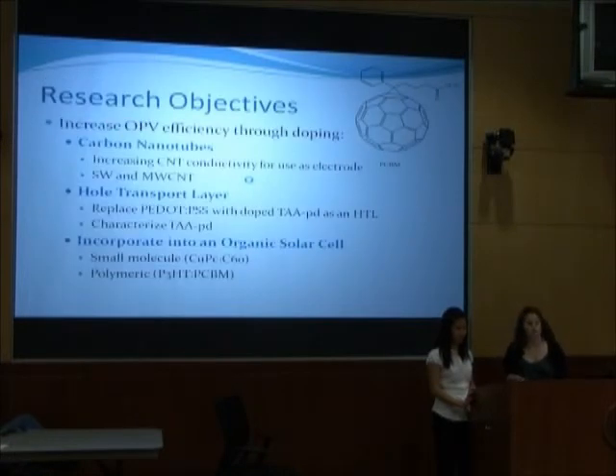In our research, our main objective was to increase organic solar cell efficiency by doping. We doped both carbon nanotubes and hole transport layers. We doped both multi and single-walled carbon nanotubes so we could increase their conductivity so they could be used as electrodes in solar cells. We did this because carbon nanotubes are both transparent and flexible, much like the solar cells we wanted to create.